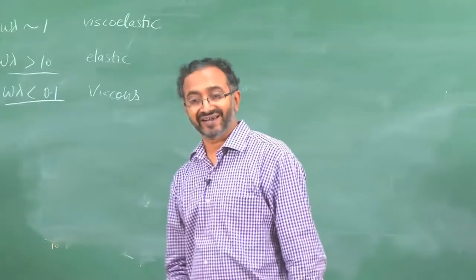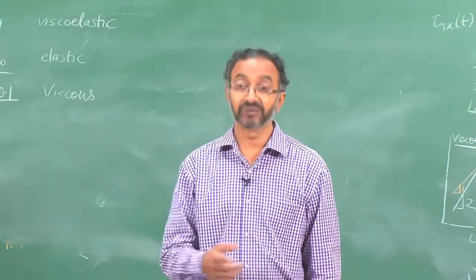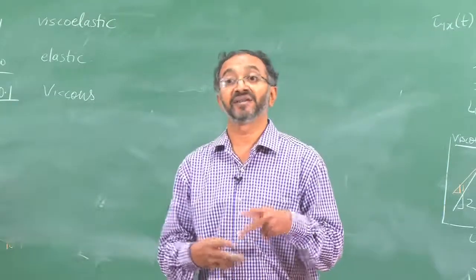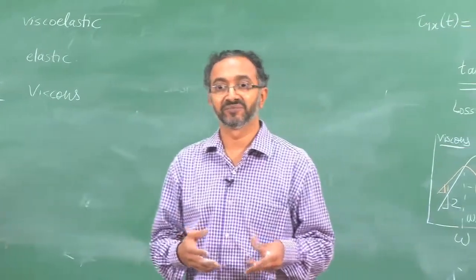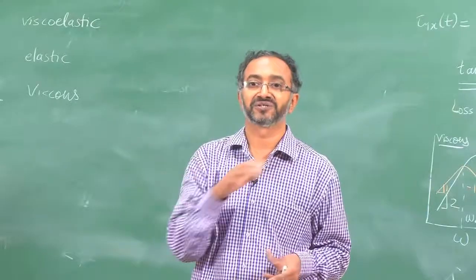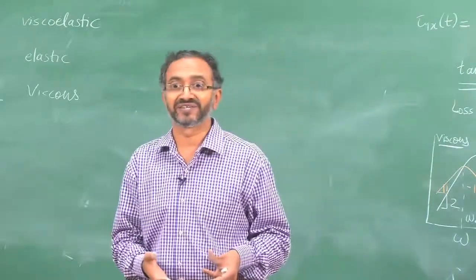Depends again. That depends on the inter-droplet interactions. It is possible at times that if there are sufficient number of charges, or let us say polymers which are adsorbed on the droplets, then the droplets will in fact remain bonded even at low frequency, and those emulsions even at low frequency will give us a constant G prime or a constant G double prime. So in fact that is a very good indication. That is why we do these kinds of tests, right. By measuring G prime and G double prime as a function of frequency, I can tell something about the microstructure.